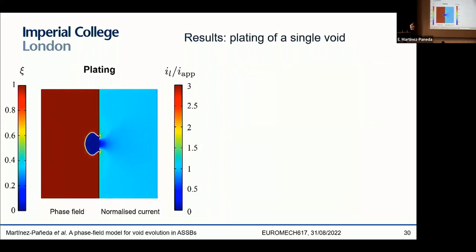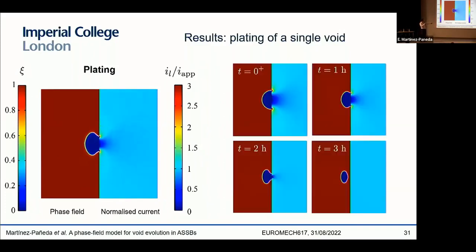Regarding plating, you can see the results here. Again, phase field on the left, normalized current on the right, and you can see essentially the same qualitative features that we saw in the experiment. So as you deposit lithium, you are closing the void, and those current hotspots eventually disappear. And if you plate for a sufficiently long time, you even see what you see in the experiment, this kind of isolation or occluded voids that separate themselves from the interface. And yeah, again, you can see it here, that eventually you do get that kind of void occlusion that you see in the experiment as well.